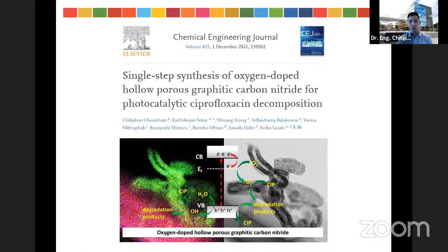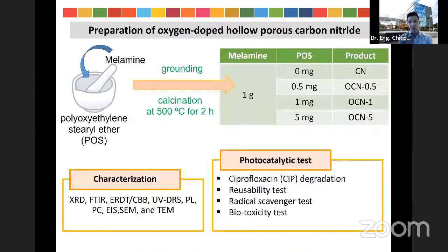Also, we have another work about the modification of the morphology of the graphite carbon nitride and co-doping with oxygen into the graphite carbon nitride structure. In this work, we prepared the oxygen-doped hollow porous graphite carbon nitride by one-pot synthesis, as shown here. So first, the polyoxyethylene stearyl ether, or POS, was utilized as a template and oxygen source to produce the hollow structure of the graphite carbon nitride and oxygen-doped graphite carbon nitride.